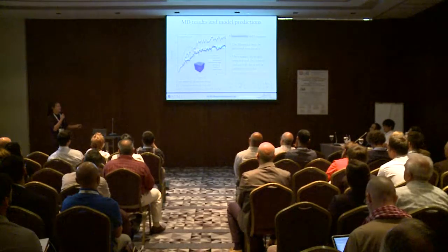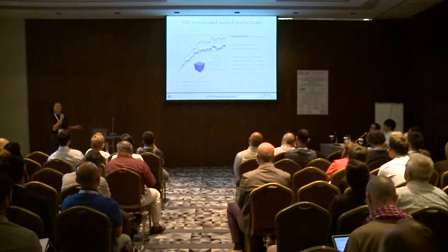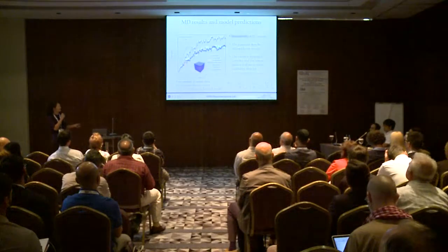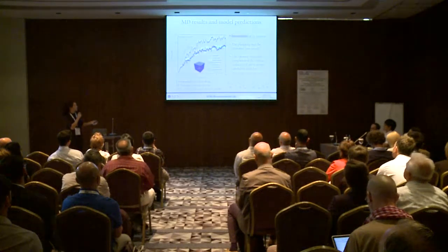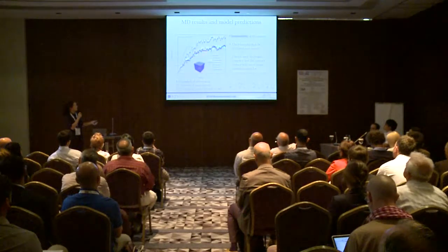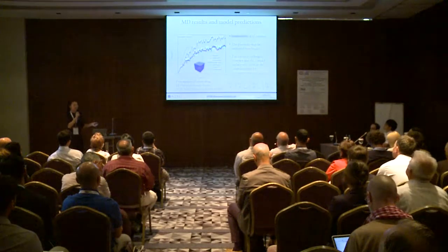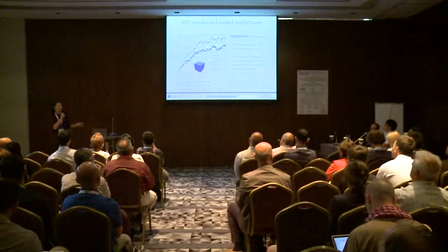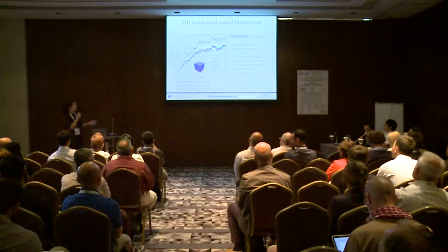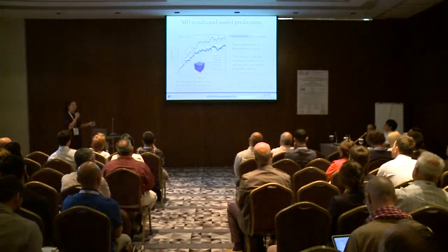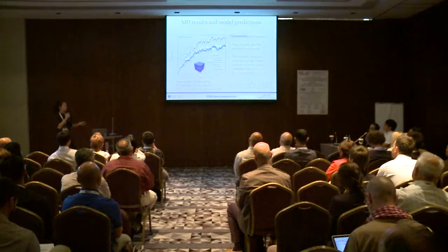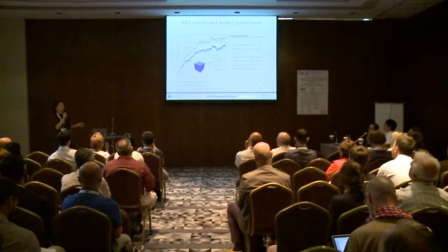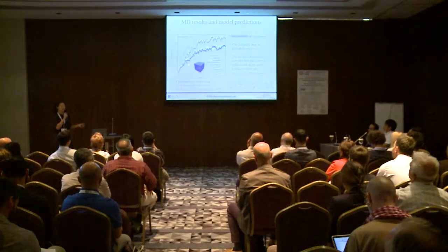However, in both cases we found insensitivity to the hydrogen concentration, especially in the molecular simulation, where the three hydrogen concentrations show similar behavior. We think the reason can be that the hydrogen atom concentration is already high, so further increasing the concentration won't really influence the behavior.